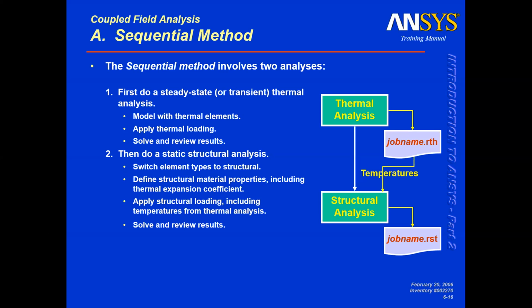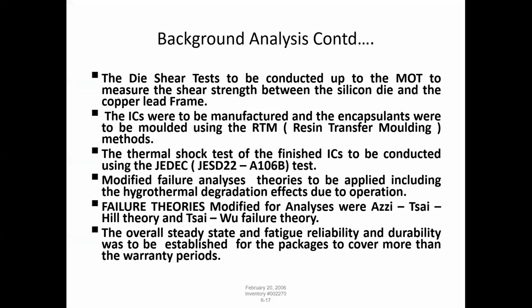So first, we did a steady state thermal analysis, got the job name .rth thermal file out, and then temperatures were input into the structural analysis, where we got the job name .rst out. So we had to do a coupled analysis and then incorporate the effects of moisture into it. So die shear tests were conducted up to the maximum operating temperature to measure the shear strength between the silicon die and the copper lead frame. ICs were to be manufactured and encapsulations were to be molded using RTM. We did resin transfer molding at the company itself. The thermal shock test of the finished ICs was to be conducted using JEDEC, the A106B test, and modified failure analysis theories were to be applied, including the hygrothermal degradation effects,